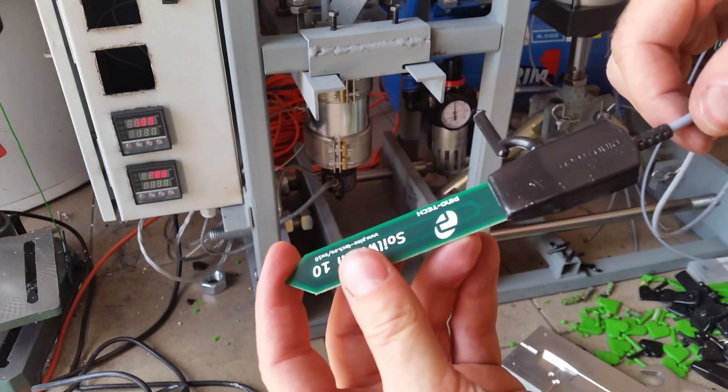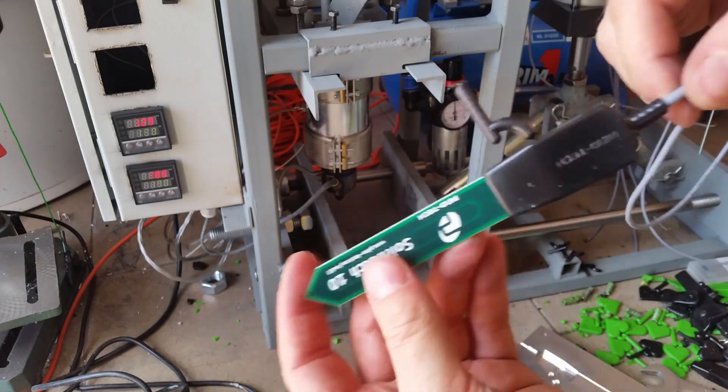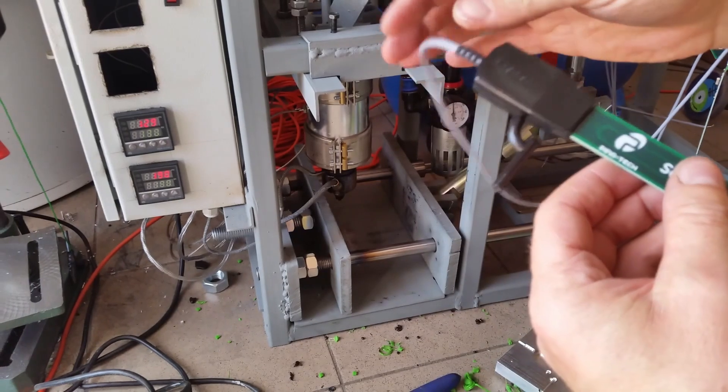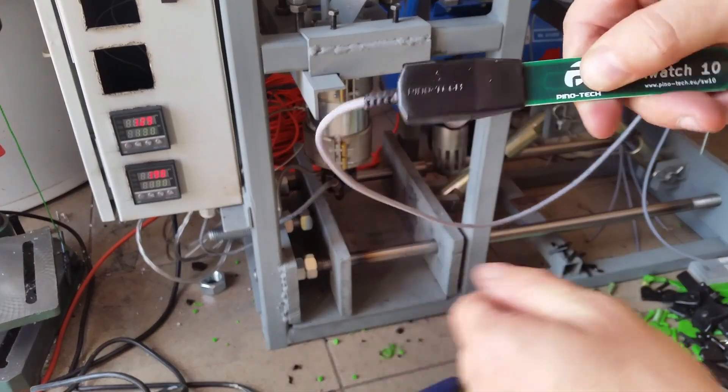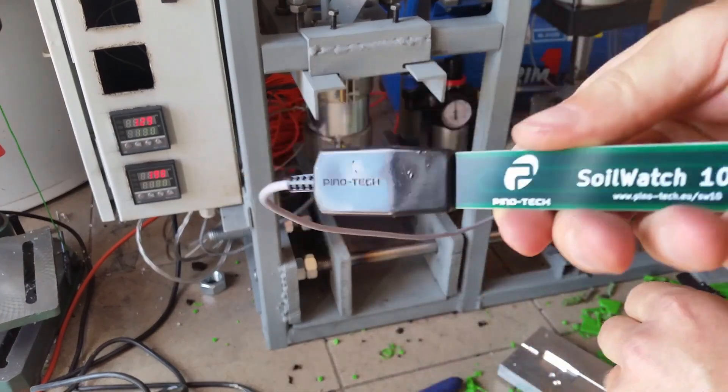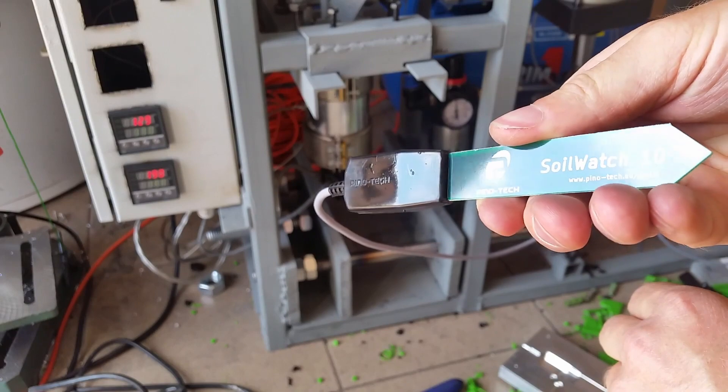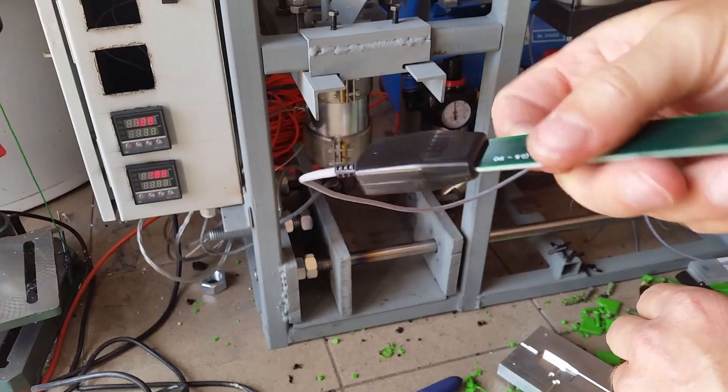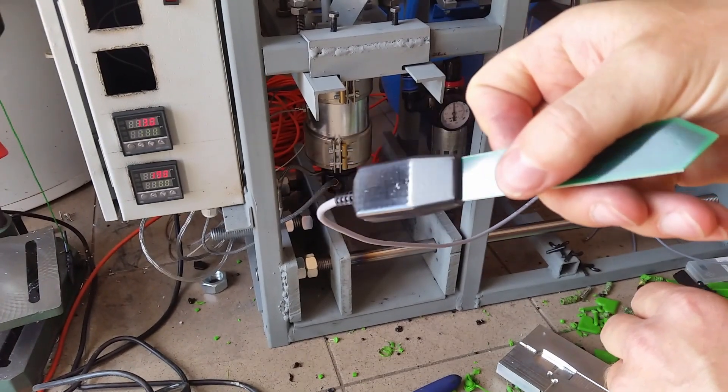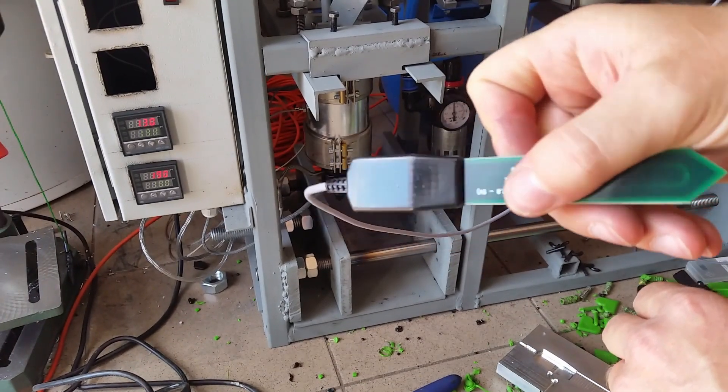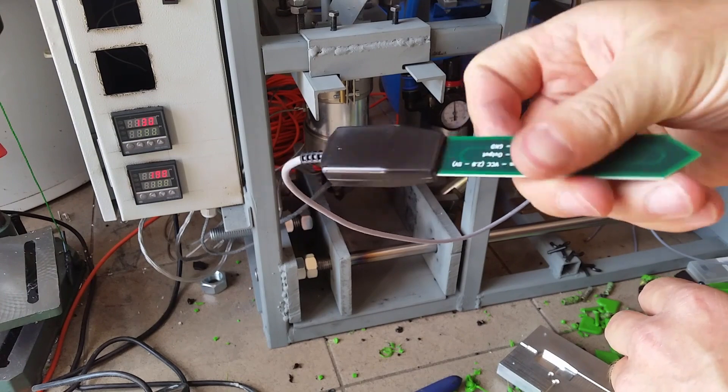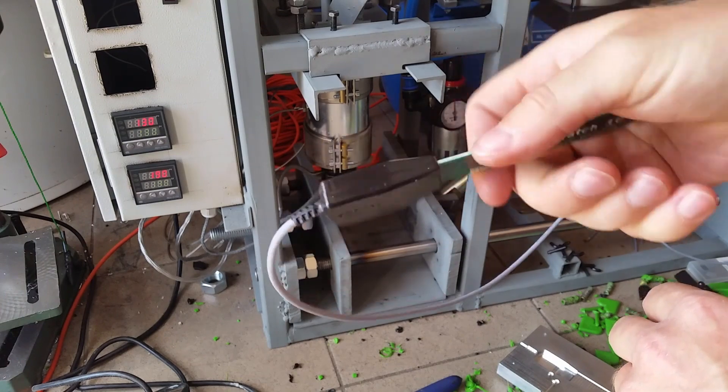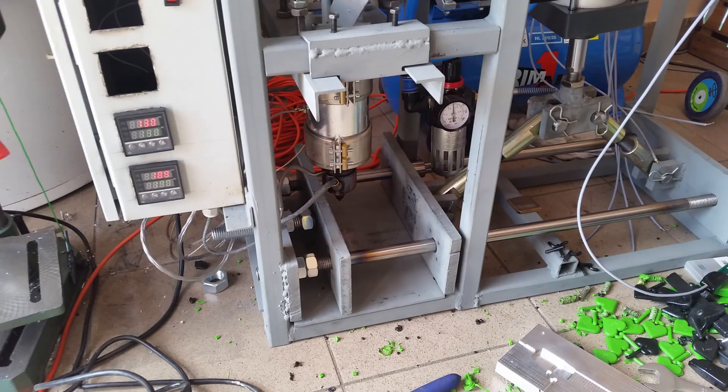You can see there's a small sink mark on the surface. That's probably due to the plastic being a little bit too hot, and also a few bubbles which I don't know how to get rid of.